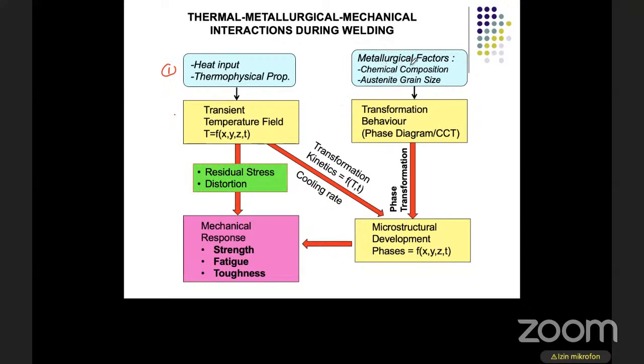On the other hand, the metallurgical factor plays an important role in affecting the final microstructure. You can see that metallurgical factors such as chemical composition and austenite grain size can affect transformation behavior, which can be seen from the phase diagram and continuous cooling transformation. And on the other hand, the heat input can influence the cooling rate, so the combined effect between cooling rate and metallurgical factor produces the final microstructure.